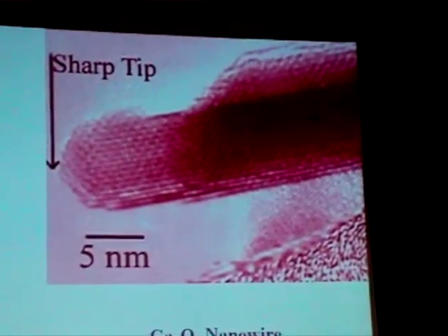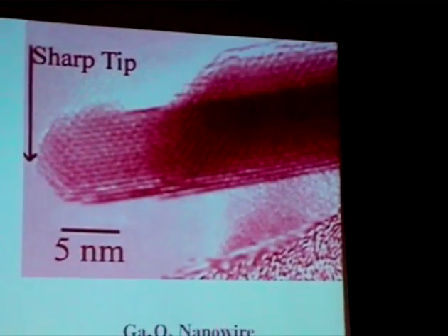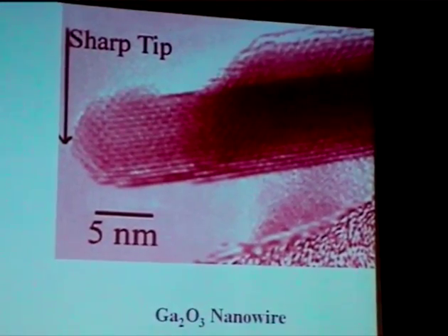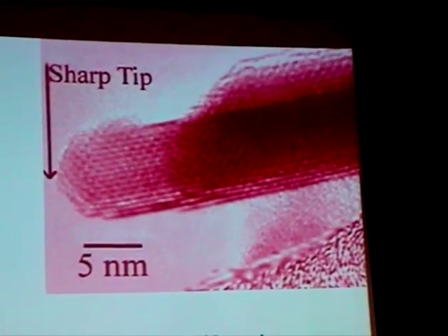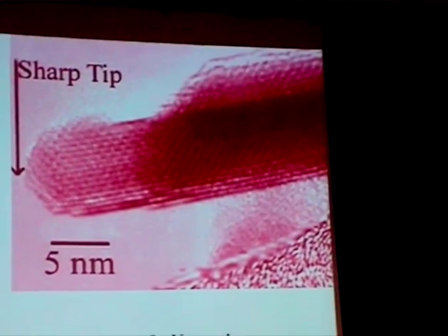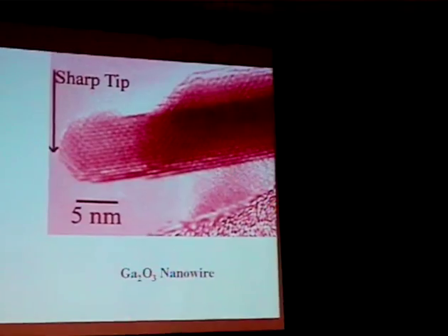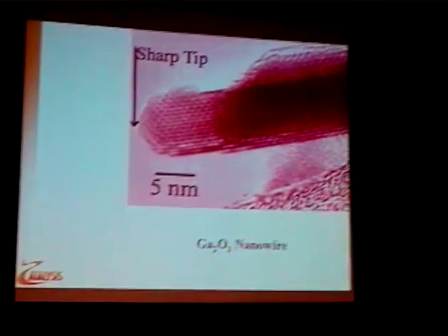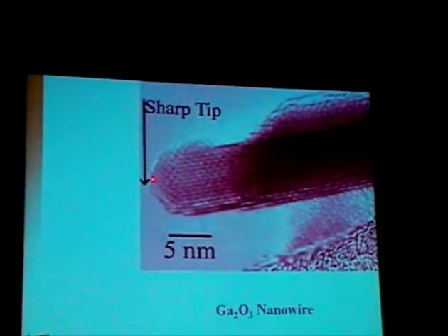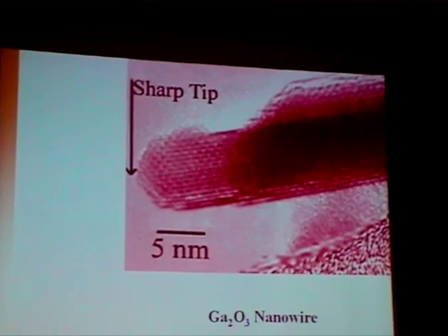We felt that we should do one other experiment to see what would happen if we would take these nanowebs and resubmit them to a hydrogen plasma. In other words, now you have these two-dimensional arrangements of wires. What would happen if we re-exposed them to a hydrogen plasma and then again a mixed plasma? This is what the result was. Instead of forming the tubular structures, now we're forming elongated single crystal structures, but again with a very sharp tip in the cap.